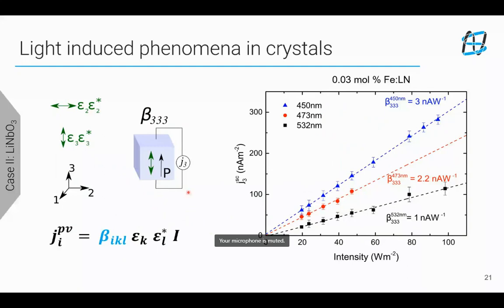We measured that at different wavelengths of light: at 532, the green light, and a blue light and a bit more towards the ultraviolet region. So 450, 470, and 532. And we noticed that as the wavelength decreased, there is an increase in the current charge density with increase in intensity of light. We increased the power or intensity of light at these different wavelengths, and we see a linear relation. So it is confirmed that the bulk photovoltaic tensor is a proportionality factor which determines the linear relationship between the current charge density and the intensity, but of course it is also dependent on the light polarization direction.